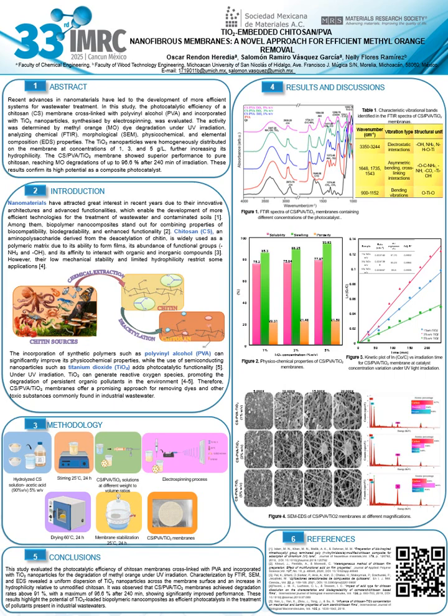About the scanning electron microscopy, it revealed a uniform distribution of nanofibers with interconnected pores, which is critical for maximizing pollutant adsorption and contact with active photocatalytic sites. Fiber diameters range from 120 to 180 nanometers for the pure chitosan PVA membranes and increase slightly with titanium dioxide loading, reaching approximately 200 to 250 nanometers at 5% titanium dioxide. This increase in diameter is attributed to the higher viscosity and conductivity of the spinning solution when titanium dioxide nanoparticles are added. Furthermore, no significant agglomeration of titanium dioxide was observed at lower loadings, while a few localized clusters appear at 5%, although they did not compromise the membrane's porosity or surface area.